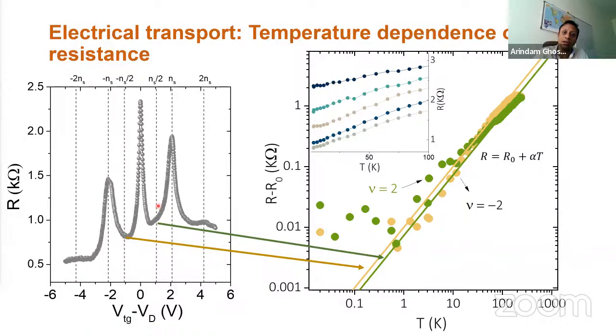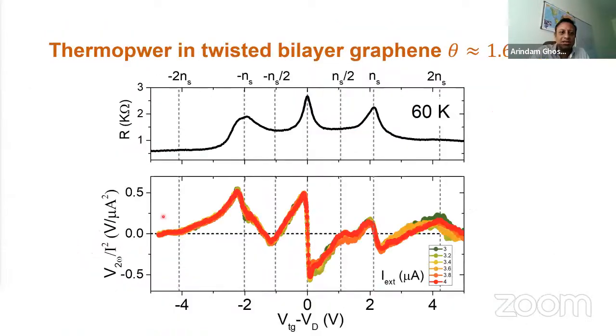Now, what happens if I do the thermoelectricity of this system? So you see, this is the 3 peaks. So if I do the thermoelectric voltage measurement, it should become a derivative of this resistance as a function of gate voltage multiplied by the density of states. Density of states was calculated by my colleague, and the electrical resistivity was measured in the experiment in the lab. So if I look at these 2 regions at half filling, this one and this one, you can see that it's essentially flat. So resistivity derivative with gate voltage should be 0. And that's what we see. If we measure at high temperature, around 60 Kelvin, the thermal power is actually going to 0 at this point and at this point. Okay.